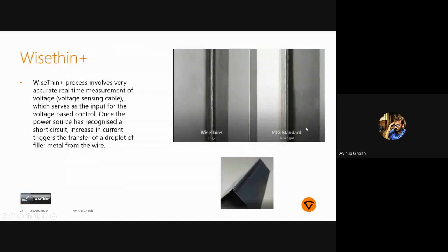Moving to the third adaptive software, which is called the Wise Thin software. This is a cold welding process where the wire that is being transferred to the material is much colder than any other process currently available. This is basically a short circuit process, and it gives a lesser heat input even with normal MIG-MAG welding with mixed gas. As gas plays a very vital part, you all know that argon CO2 gives a much lesser heat input to the base material. But practically speaking, when we use Wise Thin Plus, even with CO2, we have achieved lesser heat input to the base material.